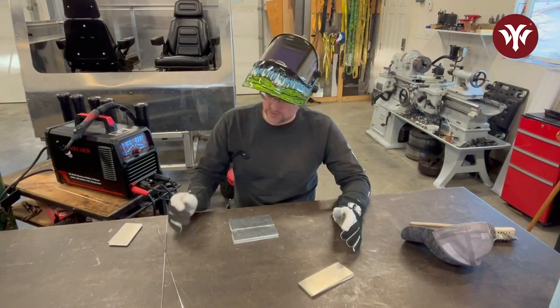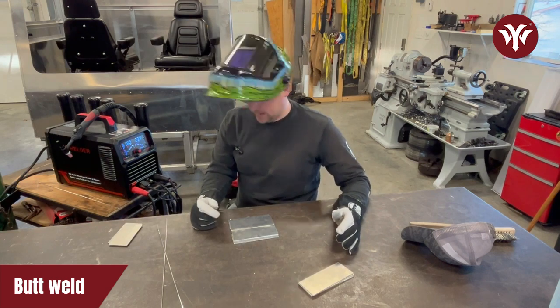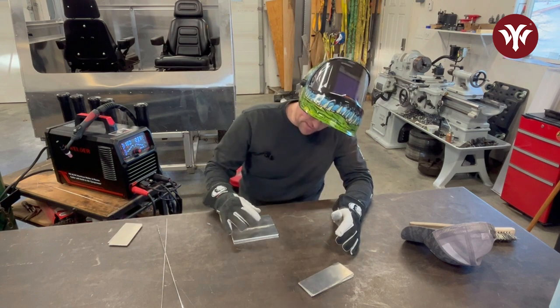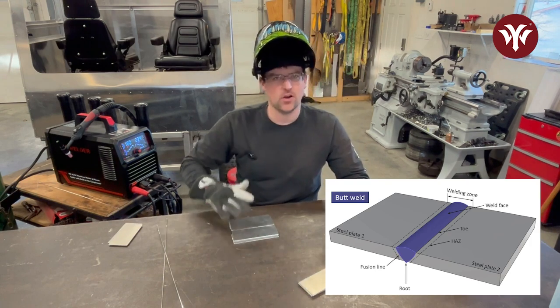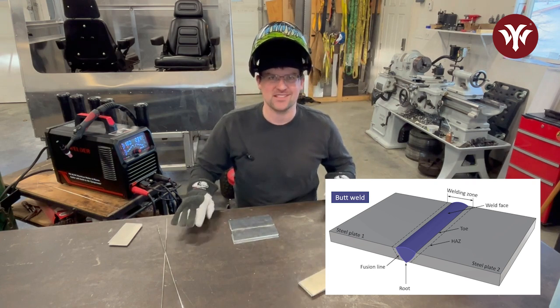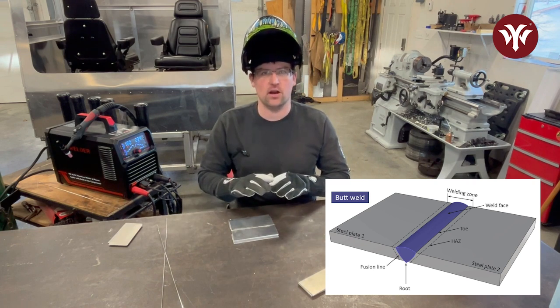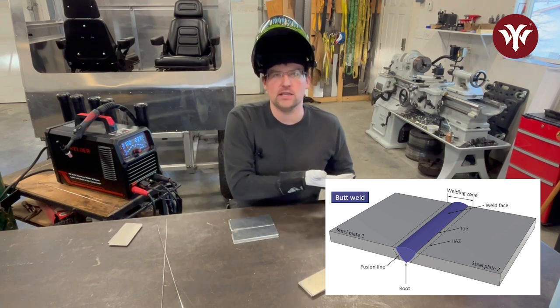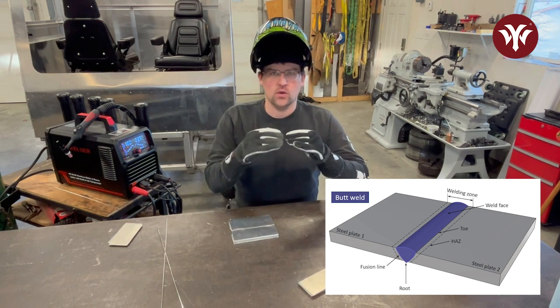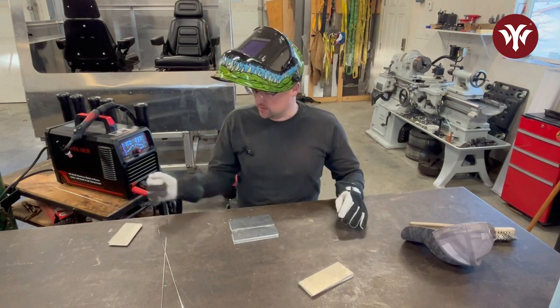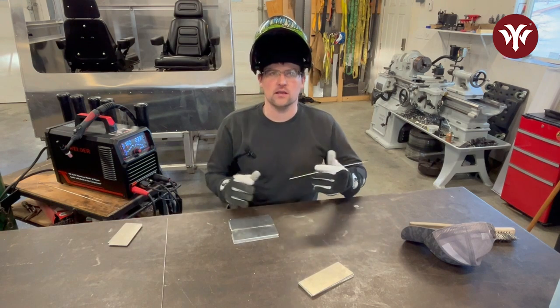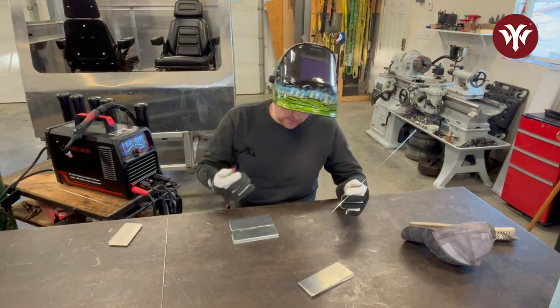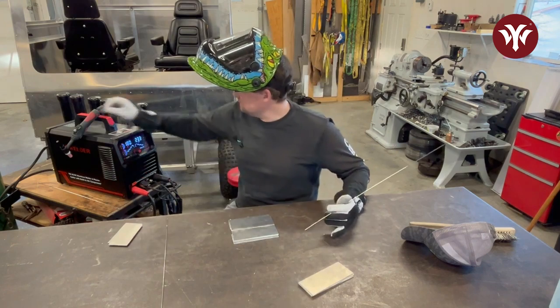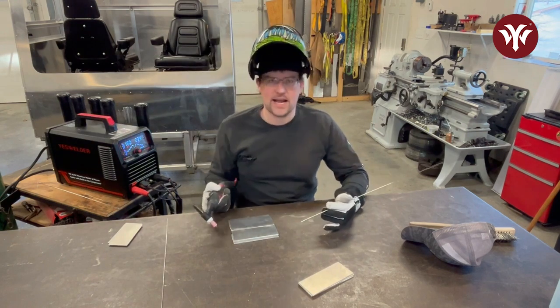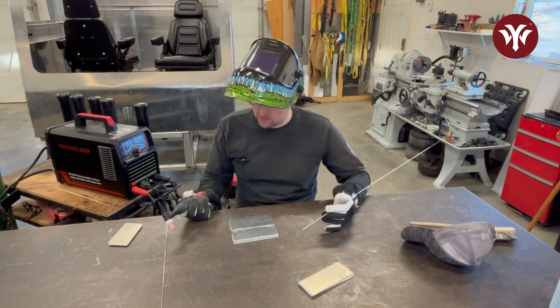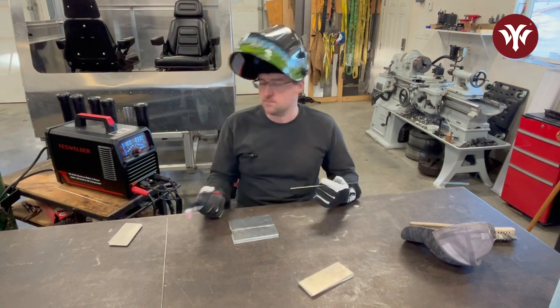The first weld we're going to do is just a simple butt weld. And if you've noticed, what I did was space my two weld coupons off this table. This is a 1/2 inch thick steel table. If I laid those down right on there, it's going to really pull heat out of the weld joint right where they meet, and it can give you a little problems trying to get the molten puddle and the penetration you need. So I'm just going to space that up a little bit. I'm going to tack the start and the finish, and then I'm going to get in here and lay a bead down.